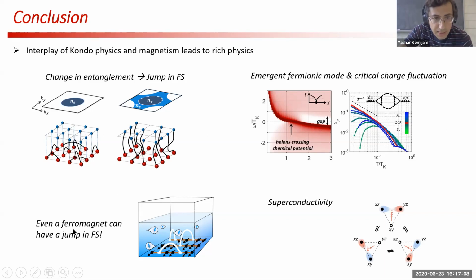So I also showed you that even a ferromagnet can have this kind of bonds, and it can also have a jump in the Fermi surface. Right? And I did not cover superconductivity, but basically it is similar. The central idea is that if we have an RVB liquid and we dope it, we get a superconductor, and these triplet RVB systems also, if we dope them, we get a triplet superconductor. This kind of physics also shows up in iron-based superconductors, where the resonating triplet is actually resonating between different orbitals of the same atom. Okay, so under the right conditions, they can go on and form a triplet superconductor. And with this, I would like to thank you for your attention.